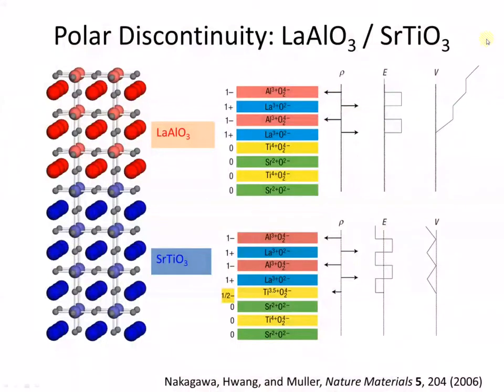So the properties of the strontium titanate are going to be influenced by a very thin layer of lanthanum aluminate. These are both by themselves nominally, when they're undoped, insulators. Lanthanum aluminate is also a wide band gap semiconductor. And when lanthanum aluminate is grown on TiO2 terminated strontium titanate, it can be modeled very simply as alternating positive and negative sheets of charge, the formal charge of these LaO and AlO2 layers. And that really means that there's a polarization which is pointing downward toward the interface. And that charge density can be represented here as a series of delta functions of alternating sign, positive and negative, which can be integrated to represent the built-in electric field in this polar material.